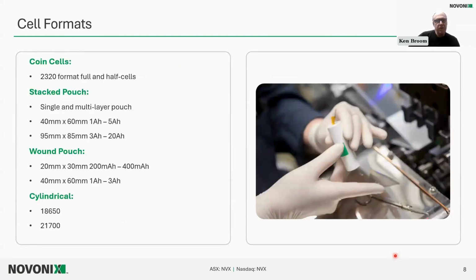So as far as the separate cell types that we make, we have 2320 format full and half coin cells. For stacked pouch, we do single and multi-layer stacked pouch cells, and in two different formats. In the smaller format, we end up with a 1 to 3 or 1 to 5 amp hour capacity cell, and the larger format we can get up as high as 20.